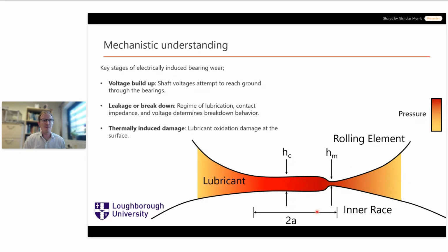When this happens, we have a significant increase in the current flow between the surfaces, and in a fairly small area. So these Hertzian contact half widths here are in the order of micrometers, and then the current flow in the breakdown region will be a fraction of this area. So we're talking sub-micrometer in terms of this discharge area. So we have high heat intensities, the heat per unit area from joule heating. And this can locally melt a small section of the rolling element or race surfaces. This can then cause an electrical pit to form, and or a change in the material properties as it's quenched by the lubricant that is next to it. So we get this thermal damage to the metal surfaces of the rolling element or races, and that can also over time damage the lubricants as well.